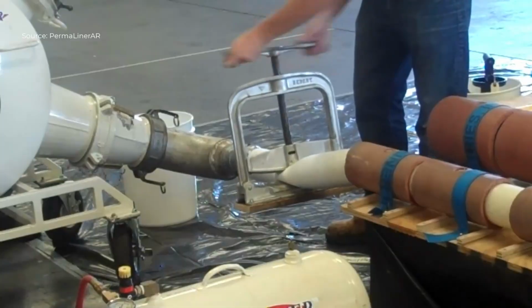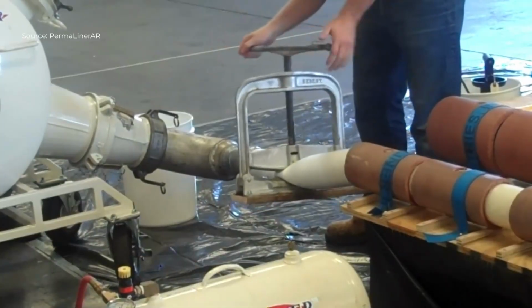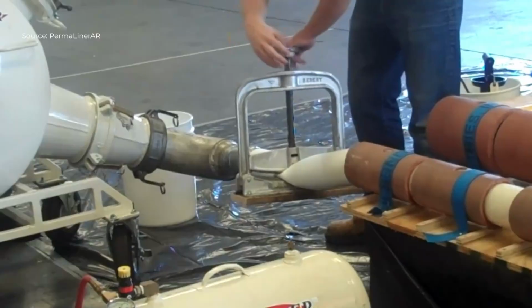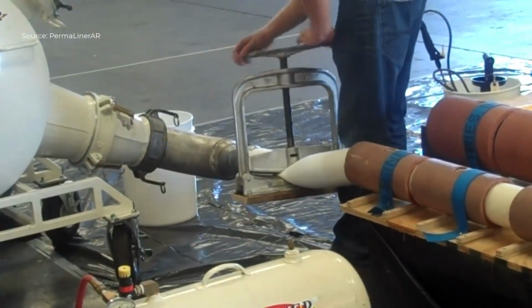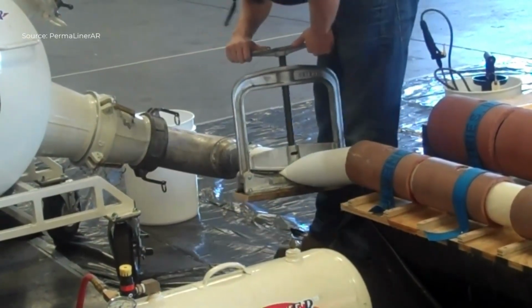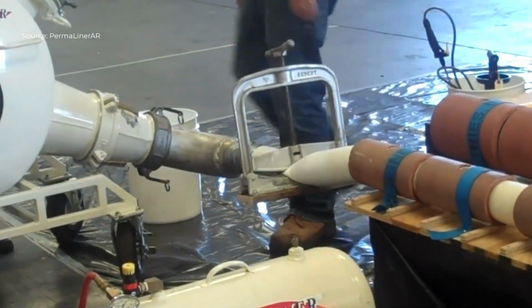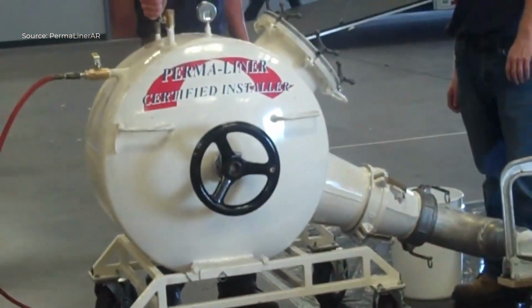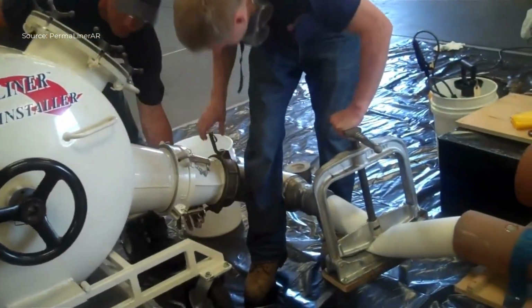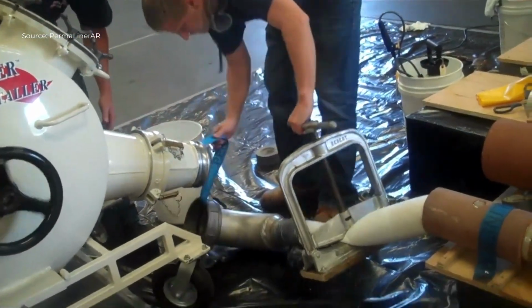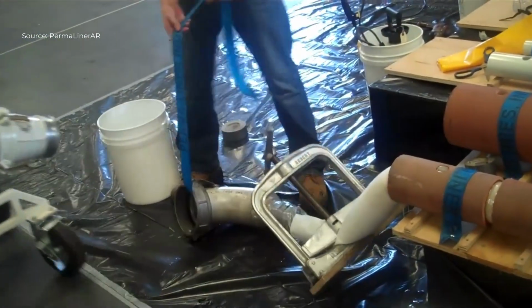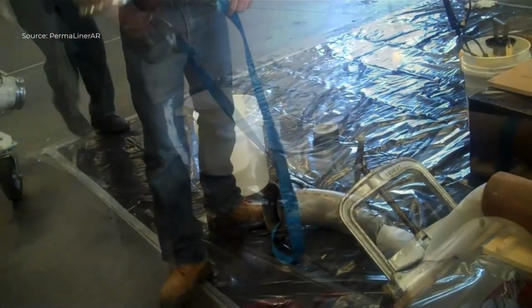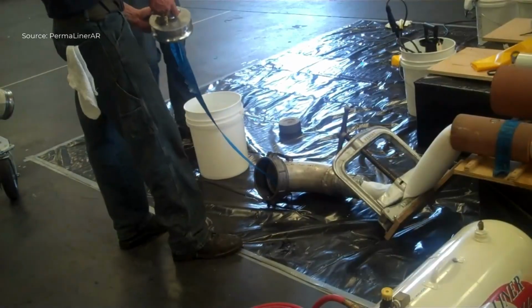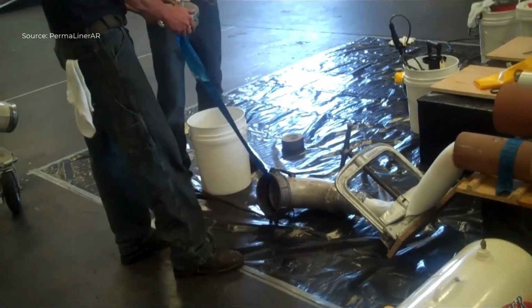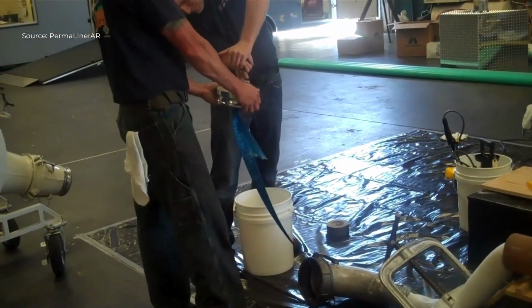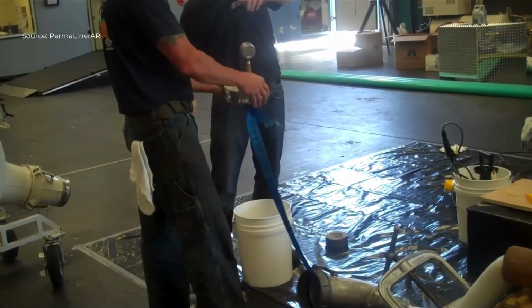Finally, after curing, the calibration tube is pulled out by means of a strap, leaving the cured liner in place. The end result is a fully rehabilitated lateral that possesses several advantages. It has structural strength equivalent to or greater than a new pipe. It also guarantees zero shrinkage, ensuring that the liner remains tight against the pipe walls. Additionally, it eliminates infiltration and exfiltration, thereby preventing groundwater from entering and sewage from escaping. Furthermore, the liner resists corrosion, root intrusion, and soil movement, which are common causes of pipeline deterioration.